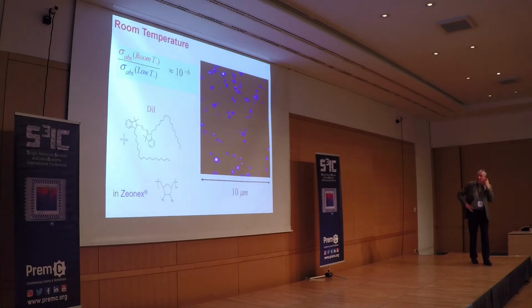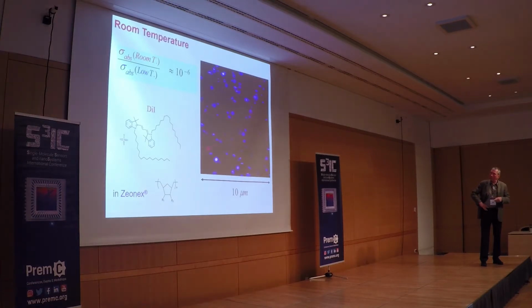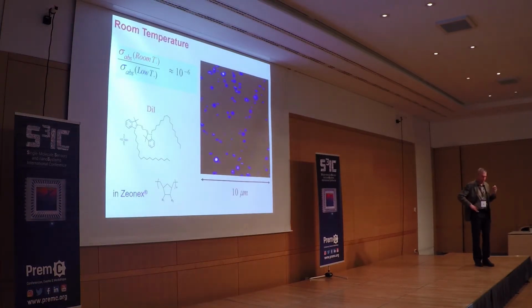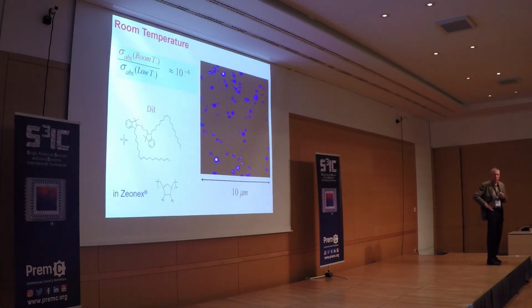Right, so this is a typical image of single molecules acquired in a confocal mode. What we do is scan our excitation laser, raster scan, across the sample. Yes, here it is. So this is my laser, so I need some training to have the proper scanning. So this is the way it goes with a raster scan. And whenever the laser spot, the diffraction limited spot, hits an emitter, a molecule in this case, we get a fluorescent signal. And we plot this fluorescent signal in this image as a function of position. And this gives you an image where you see single molecules. In this case, the molecules are blinking. I will not discuss this now.